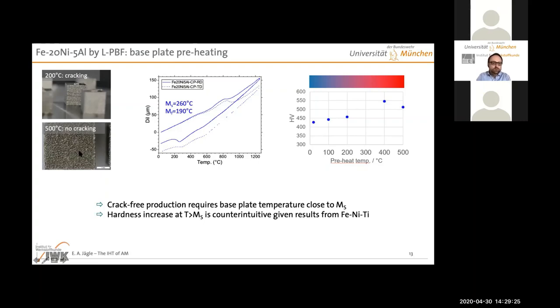So what do we do? We just flip on our base plate heating and we go to 500 degrees. Why 500 degrees? Because it's above the martensite start temperature. If you look at this dilatometry curve, only below 260 do you get some martensite transformation. And that allows us to produce completely crack-free specimens. So that's a success from the processing side.